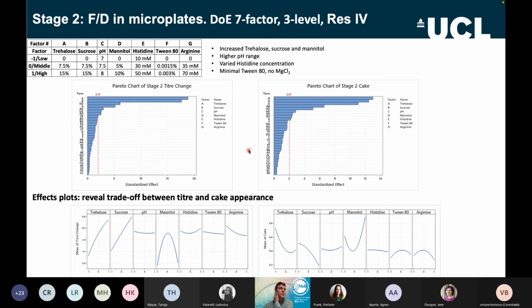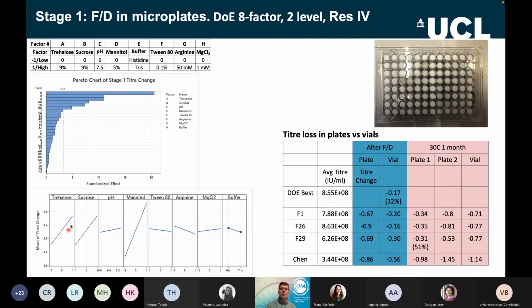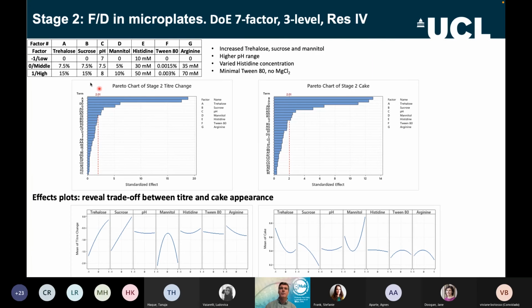So stage 2 was to explore in more detail, because the previous stage was only 2 levels. It doesn't really tell you where the optimum is. So we put in a third level, so we now have a low, middle, and high level. We also increased the concentration range for trehalose and sucrose. That's because, as you can see here, they seem to be going up, and we're not yet reaching a maximum, so we could add more. So we went up to now 15% of each of those sugars.